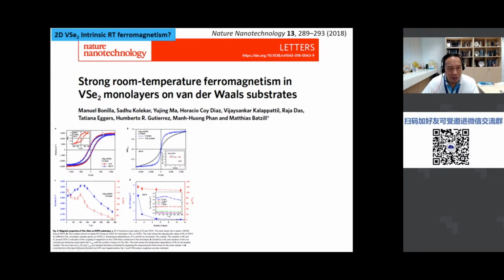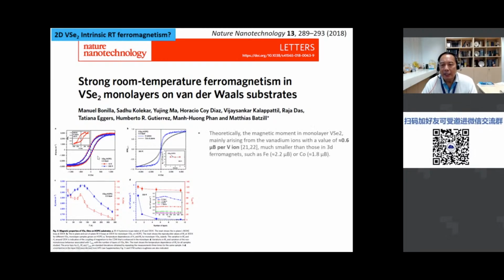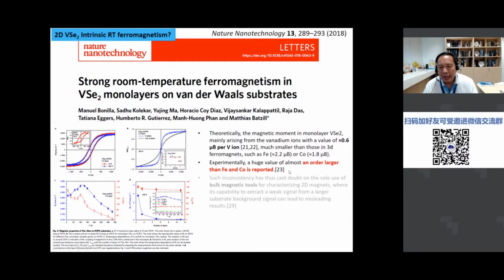So you see this hysteresis loop, and essentially, theories have already predicted that the vanadium ions have a value of 0.6 Bohr magneton per vanadium ion, although it's smaller than other 3D ferromagnets like iron or cobalt. And they reported, strangely, a huge value that is about an order of magnitude larger than the theory. So this was something that was not explained in the paper. And this inconsistency cast doubt on the use of bulk magnetic tools, because they use bulk magnetic tools to measure these MH curves.